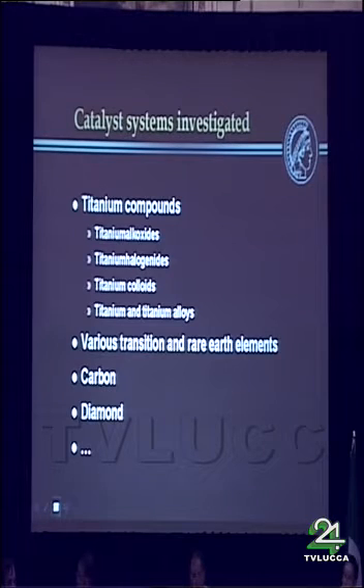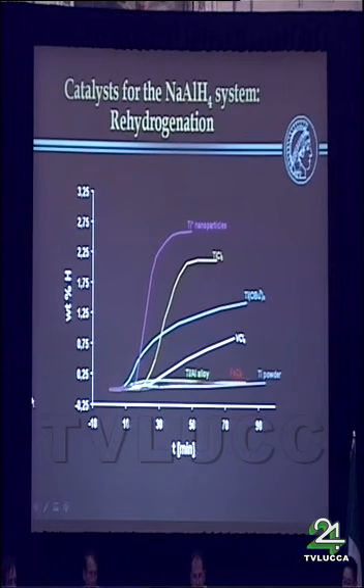Titanium trifluoride comes close. I have just plotted here the rehydrogenation rates for a couple of different catalysts, which were all prepared under the same conditions. This doesn't mean that vanadium trichloride is always worse than, let's say, titanium butoxide. Each of the catalysts may have its optimized synthesis procedure for the doped material, but if you do them all the same, this is roughly the sequence of activities we find.